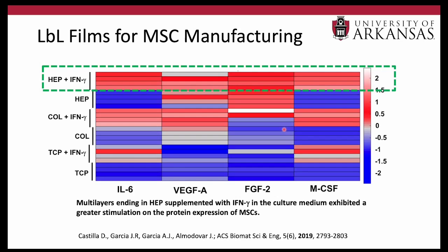We investigated protein expression, and this heat map shows 4 different proteins that are very important in the immune properties and also in tissue regeneration, in angiogenesis, for example, VEGF. And we saw again that our surfaces promote the expression of all of these proteins, particularly heparin-terminated surfaces, and even more so in the presence of interferon gamma. So heparin-terminated surfaces, as shown in the top 2 rows, and particularly with interferon gamma, have a really, really high expression of all of these proteins. So that was quite favorable. That tells us that, in fact, the cells are behaving differently with these surfaces, and perhaps in a positive way.